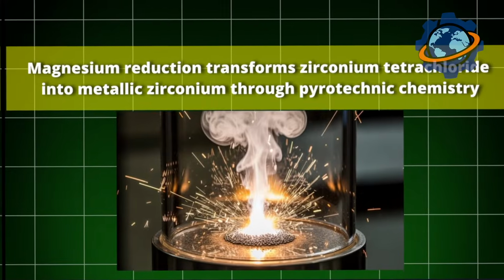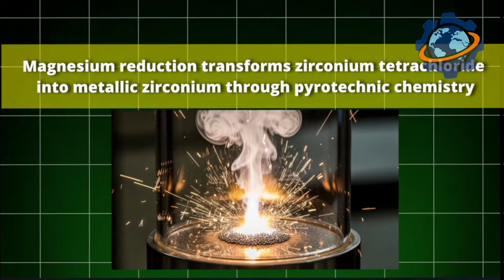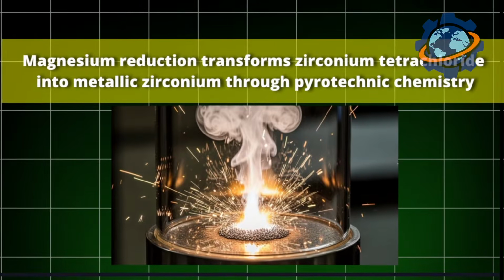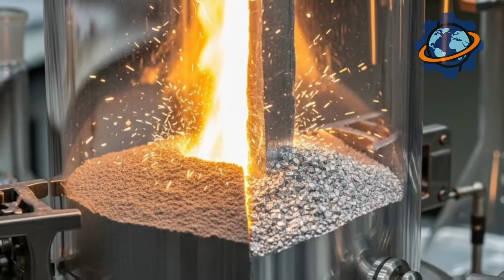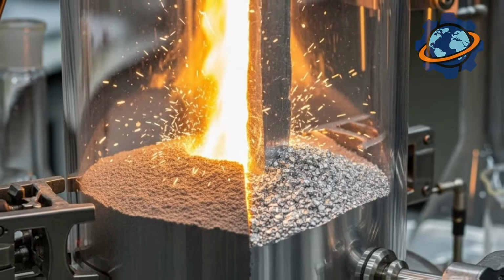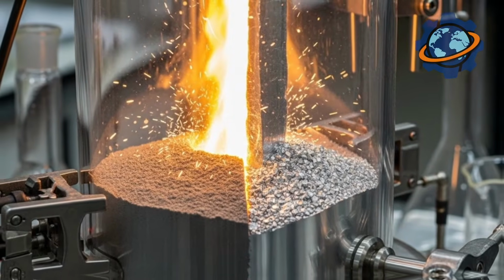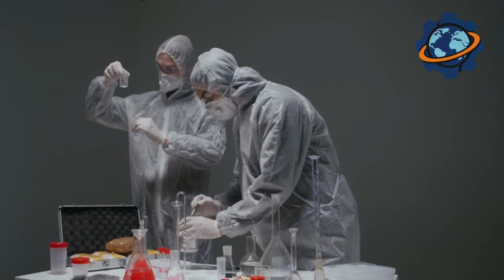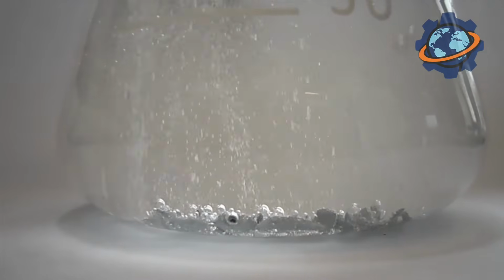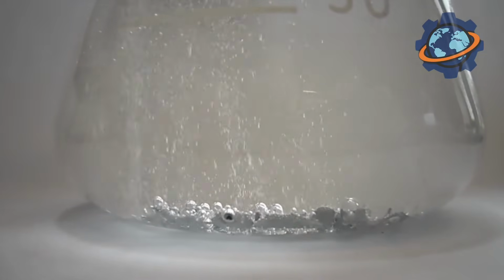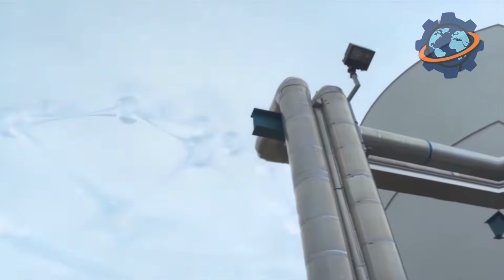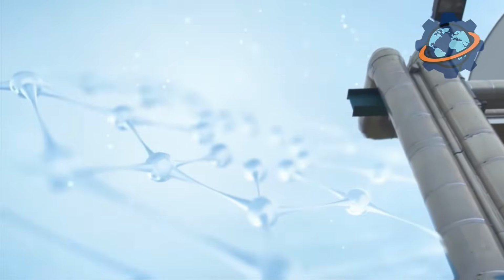Magnesium reduction transforms zirconium tetrachloride into metallic zirconium through pyrotechnic chemistry. The tetrachloride gas, cooled and purified, enters massive steel reactors containing molten magnesium, heated to 1,600 degrees. When the gases meet, a violent reaction produces zirconium sponge plus magnesium chloride salt. The heat release is so intense that reactors glow red despite foot-thick walls.